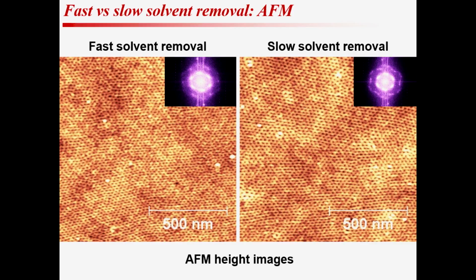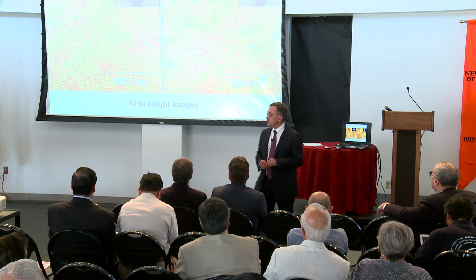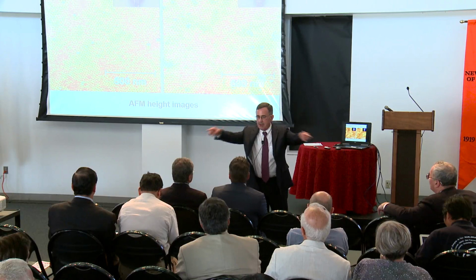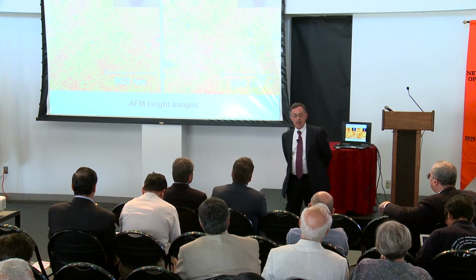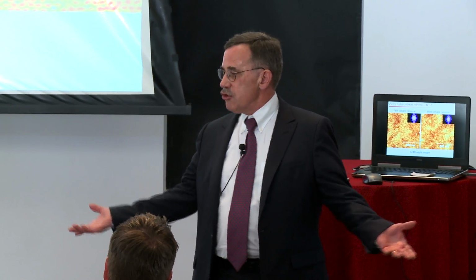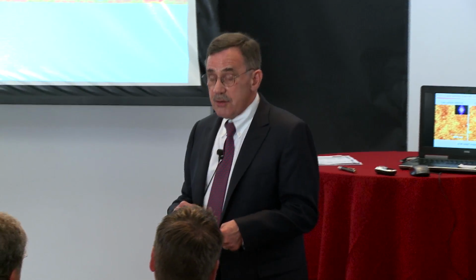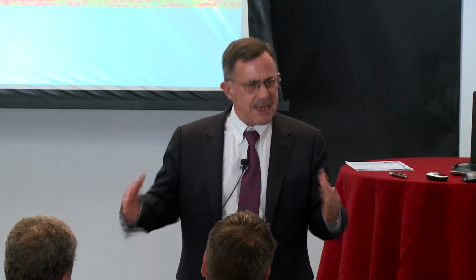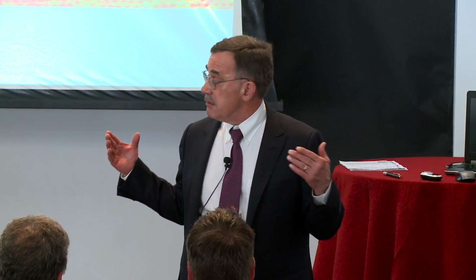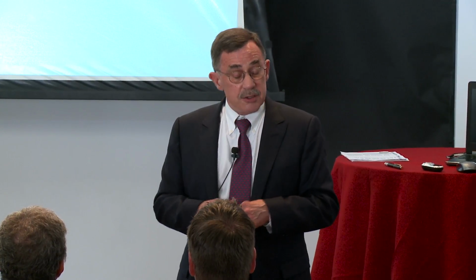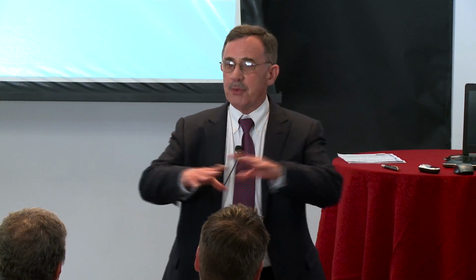And the reason for that is that as I take the solvent out slowly, I have a problem. Now, I want you to consider these chairs as being these cylindrical domains on a surface, and the surface happens to be covered by the area covered by these chairs. And as Curtis showed us, initially these chains are sort of stretched and then they compress, and at equilibrium, we can establish a finite number of these on a surface. We have a lateral surface that has a certain area. The unit cell of these structures has a finite area. So in the swollen state, they have a certain finite number of these domains on a surface. Now we remove the solvent. If we remove it rapidly, boom, we're stuck with this.